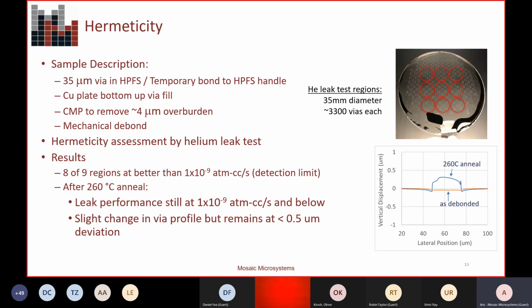And after the anneal, we still see the same performance. So the main outcome here is that you can get helium leak hermetic performance by leveraging these standard plating processes. And that's pretty important for a number of MEMS and other applications that are interested in using glass as a lid or an interposer. That hermetic performance is really important to protect those sensitive structures underneath.